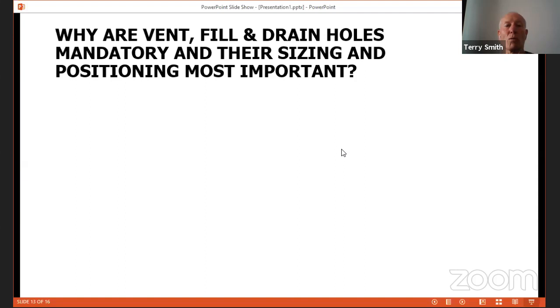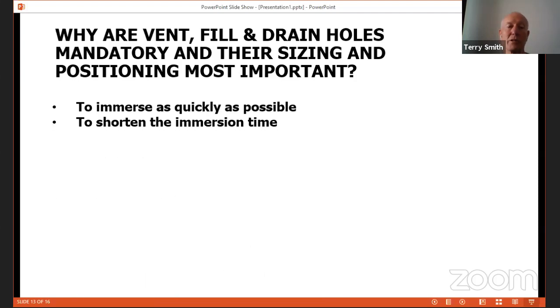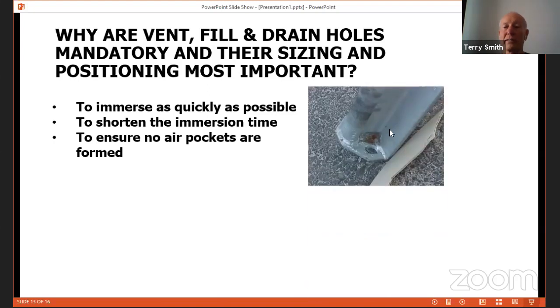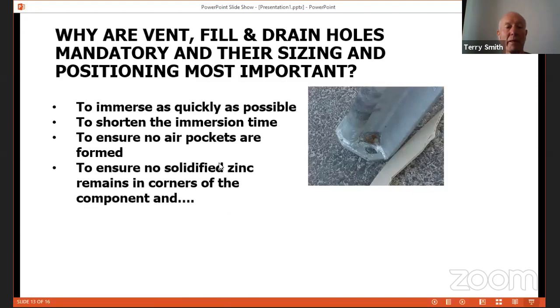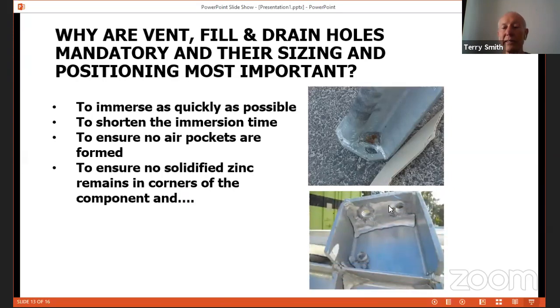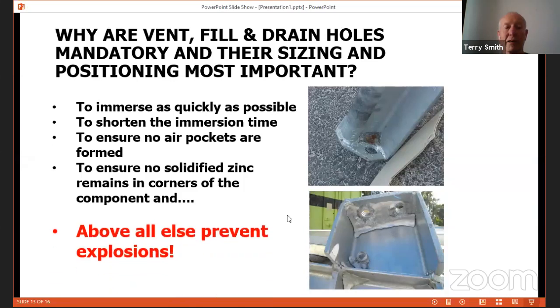So why are vent, fill, and drain holes mandatory, and their sizing and positioning most important? To immerse the item as quickly as possible in the molten zinc, to shorten the immersion time, and ensure that no air pockets are formed. Here you can see a typical example where you've got an air pocket, which obviously needs to be repaired. Also to ensure no solidified zinc remains in the corners of the component, and here you can see the zinc that has solidified in that item. Above all else, to prevent explosions.